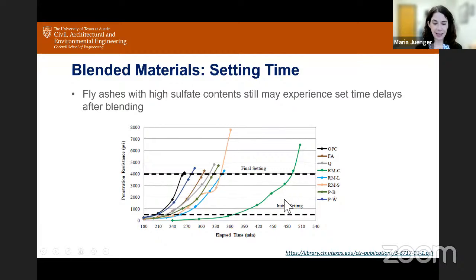This particular fly ash had a high sulfate content originally and was out of spec because of it. If you blend it with a natural Pozzolan that had no sulfates, you can get it to meet the specification and reduce that sulfate content. You dilute the sulfates that are in there, but you don't get rid of the problem caused by the sulfates, which is a delay in setting time.